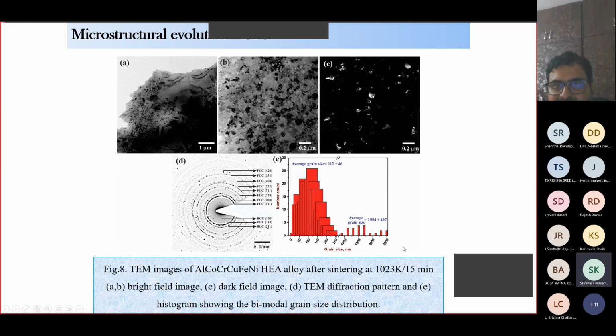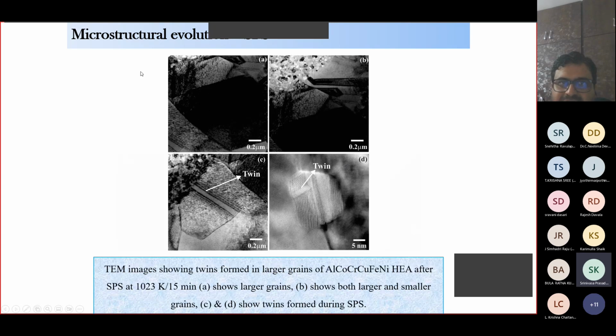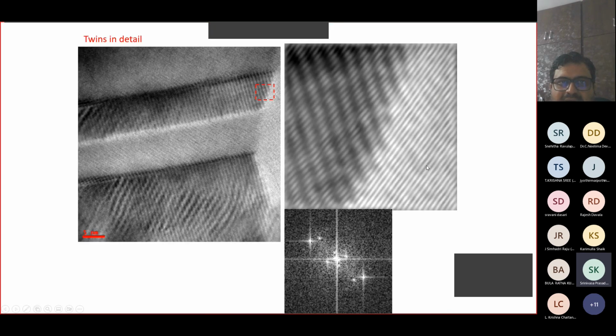And also there are some larger grains which are more than 1.5 microns. You see here large grains and also small grains here. We have twins, so many microstructural parameters. The microstructure is really, really complex. And these are the twins. We used high resolution transmission electron microscopy to understand this twin behavior. See here, we did not do anything to it. These twins have formed during heating. This is 5 nanometers. They're all atomic planes.